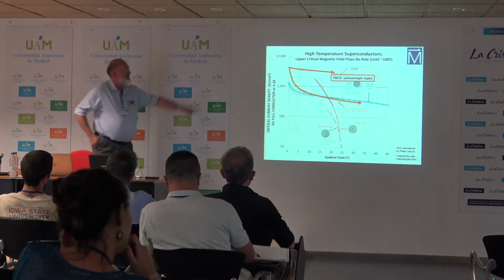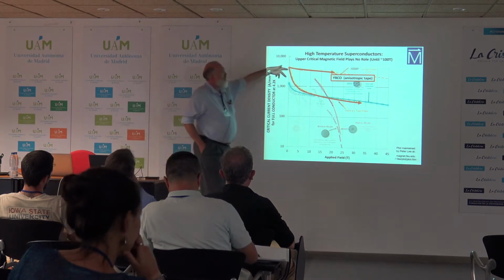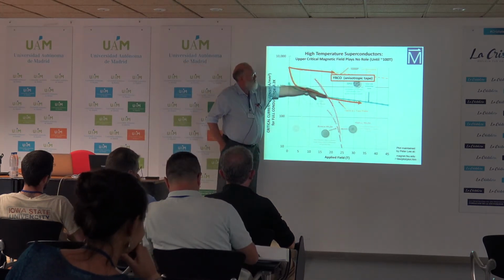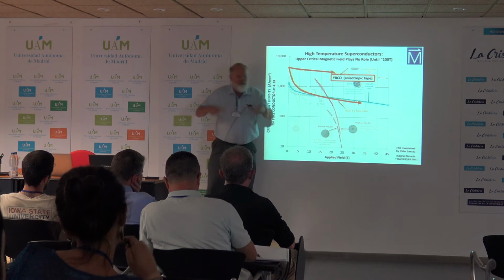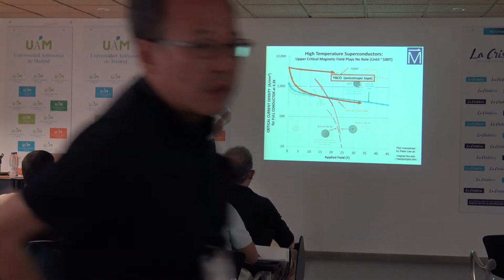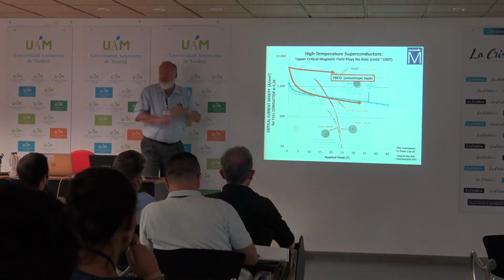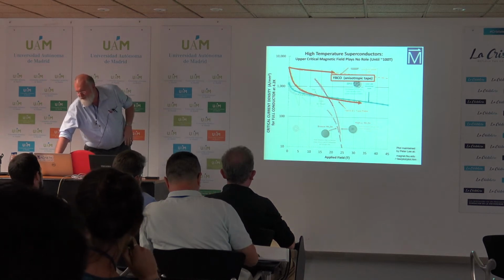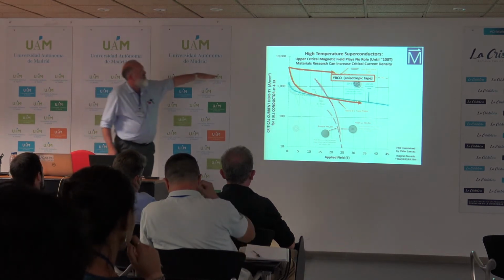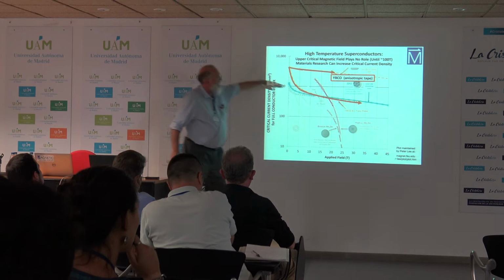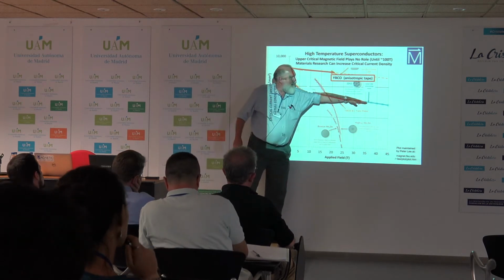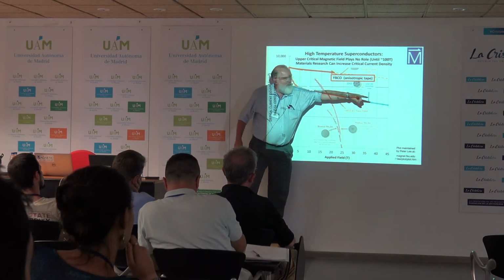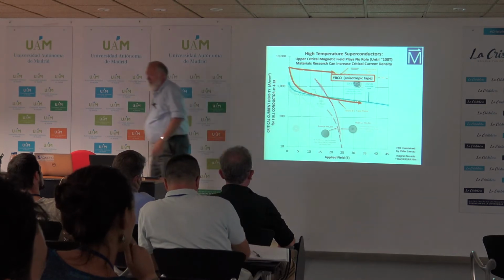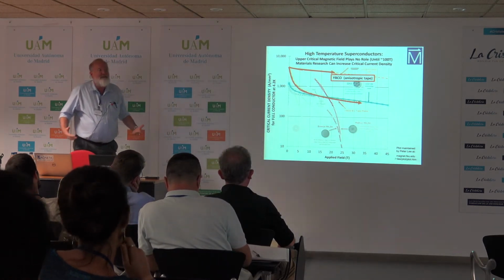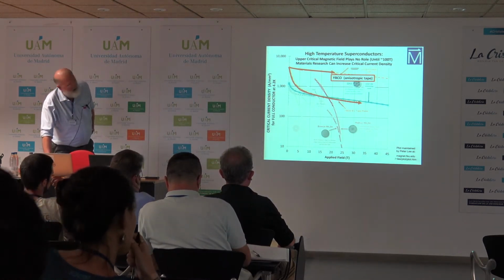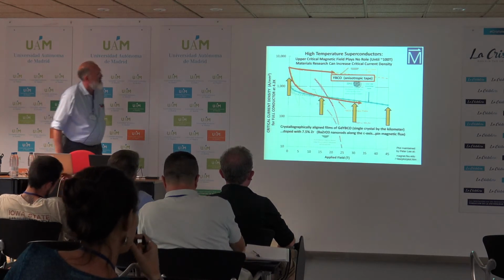compare to high Tcs? This is critical current density for YBCO tape. It's anisotropic. It has two orientations. If the field is in the plane, then you get a very high critical current density. If it's perpendicular, it's lower. But notice that these are practically horizontal lines. And so the upper critical magnetic field doesn't play a role. It's somewhere over by the wall there. In fact, we've done experiments to 100 Tesla. We've not been able to suppress superconductivity in optimally doped YBCO.